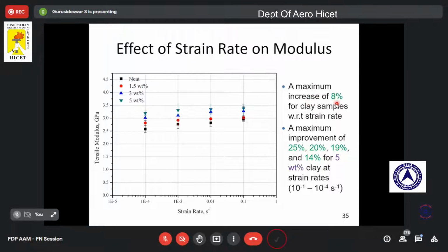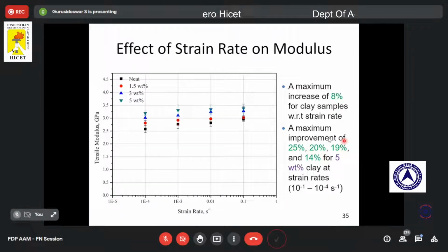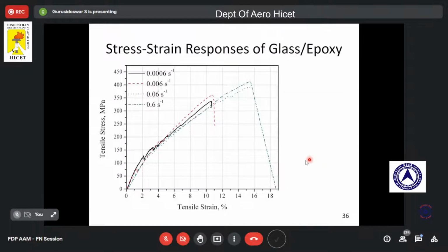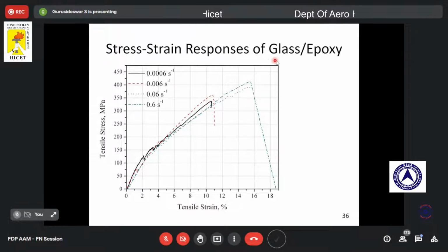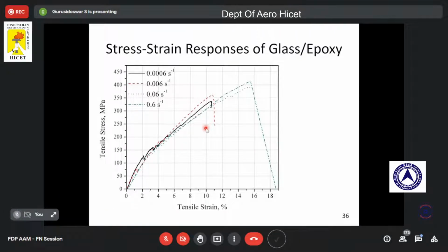So we have got an increase in the strength because of the increase in the strain rate. Here I have given the data for different samples, starting from epoxy to clay samples. Fine. Now we wanted to understand the rate sensitivity of a typical composite material. So now we have taken glass epoxy, where glass is my primary load carrying element and epoxy is the matrix. So we observe the same trend.